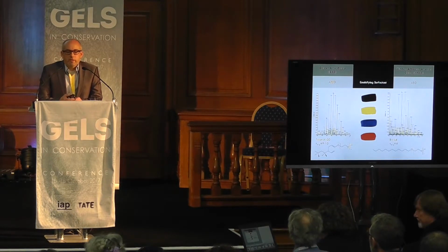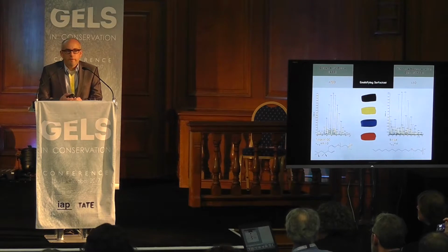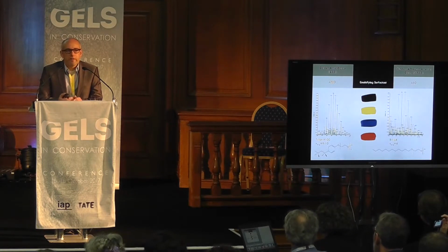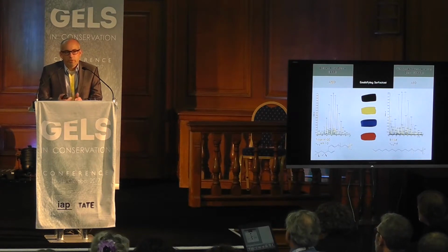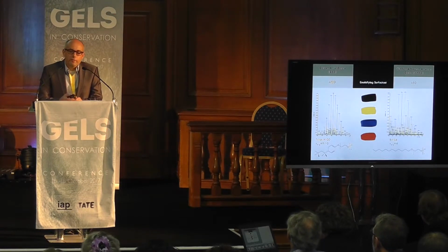And what we find in these Golden Artist Colors, and people have known this, Bronwyn Ormsby has reported extensively on this, is that they contain these alkylphenol ethoxylates. Okay, so that aromatic structure that's incorporated into that surfactant, the alkyl phenyl portion, that becomes extremely important, we found, in the soiling mechanism. In the Winsor & Newton Artisan Colors, we find a different surfactant.